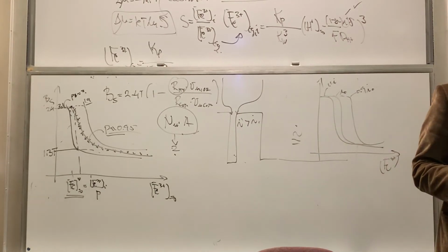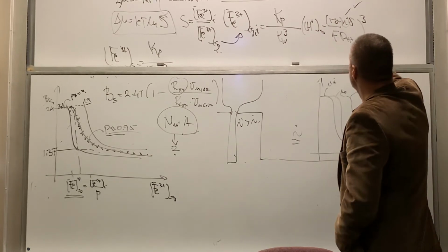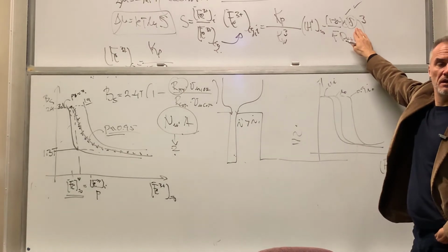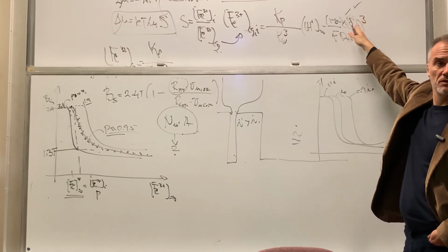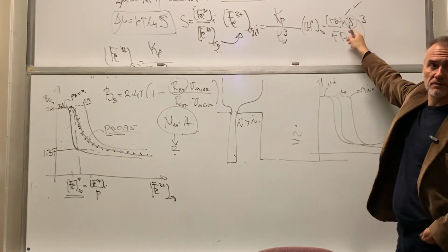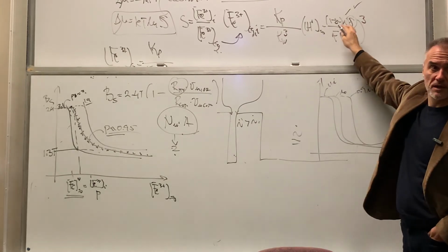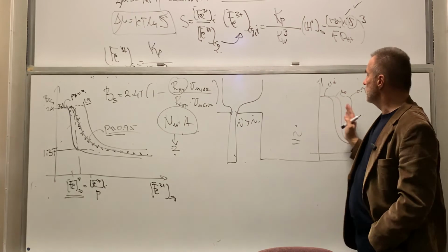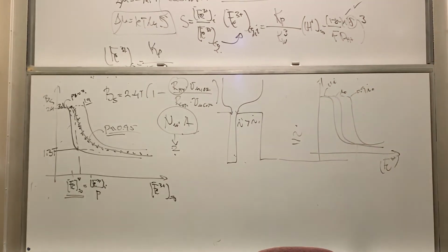You can also simulate the effect of mixing. Let's say this is stagnant electrolyte, delta diffusion layer is about 0.05 centimeters, but if you do mixing, it could be less, and you can simulate curve, and you're going to get about the same but opposite effect than the current density increase, because this increase will basically similarly show up here, right? So this is what is important.